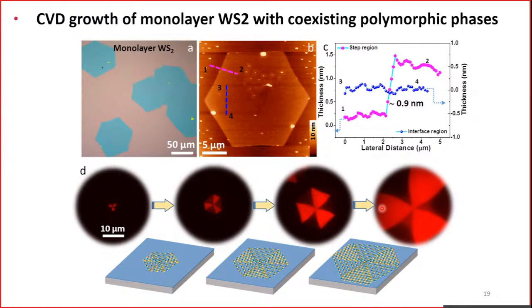The third aspect, I think, what I want to cover is, in addition to the defect and the fabrication, how do we control the phase, different allotropic phases? Again, that is also possible to achieve by CVD. This is an optical microscope image of the WS2 monolayer. We don't see any contrast. But if you look at a fluorescence image, we are essentially seeing this kind of contrast where we have self-organized alternate triangles. One is dark, one is bright, again dark, light.